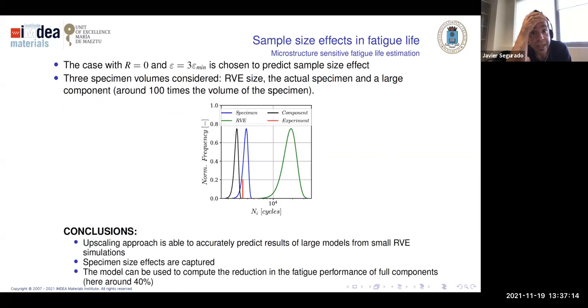The other thing is that, as I told you, there is a size effect, and the model takes the size effect into account. This is an example. This was an experiment, and for one particular case, for a given applied strain, we have that the life is this red column. Now with the model, with a very simple equation, that is the Gumbel equation that I have shown, we can predict what would be the life of a very big part made from this material, that the life would be this one, or the life of a very small specimen that would be something like this one. And this is something that the industry observes.